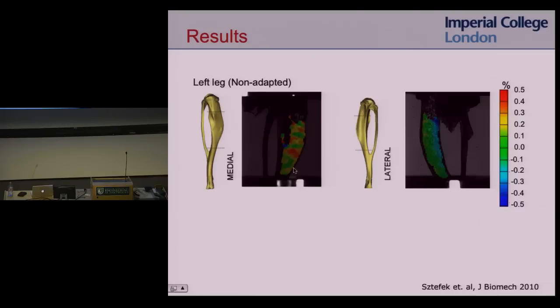And we're looking at the, ooh, that's really dark. We're looking at the medial side and the lateral side. So red here is positive and blue is negative strain, so compression. So we're actually applying a compression, but you see some red spots here. And that's because the tibia is bent like this. So if you apply compression, you actually get bending. So you get compression on one side and tension on the other side. So that's why we have tension here.